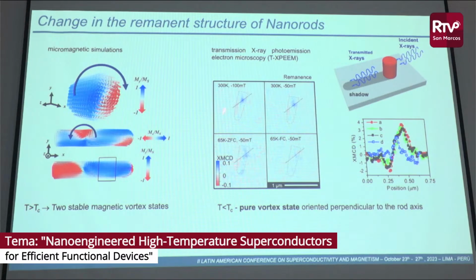And in all these structures, we more or less reproduce what we have here theoretically with the stabilization of these two vortex states. When we go below Tc, we see a contrast which is different, and if we go below Tc with a field cool, which means that we have trapped magnetic field in the superconductor, we're able to change the structure of this rod with two vortices to a pure vortex state.